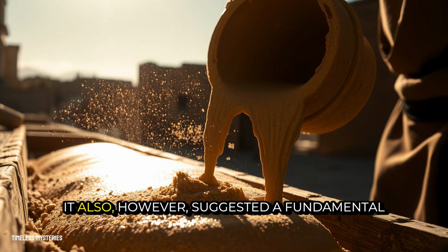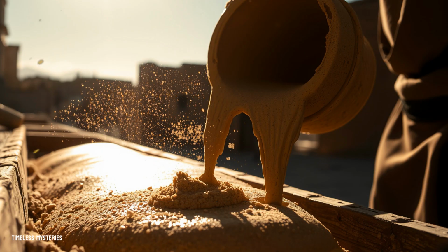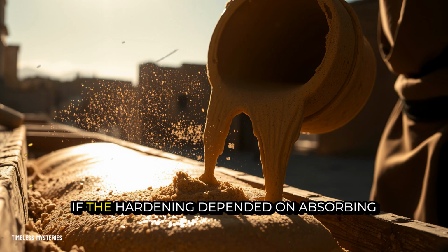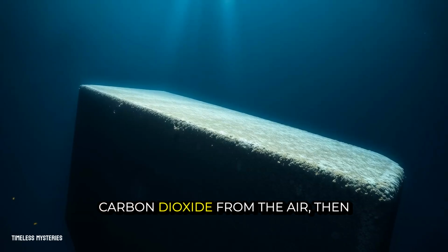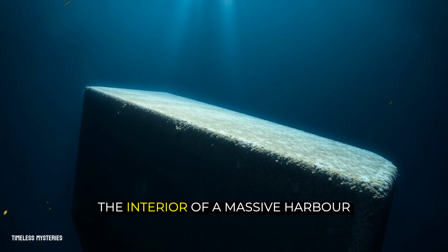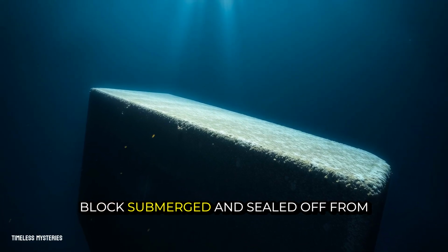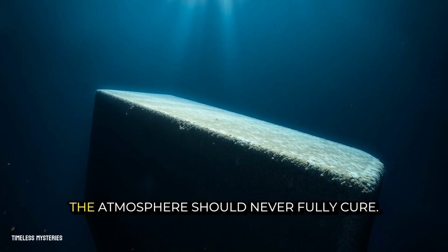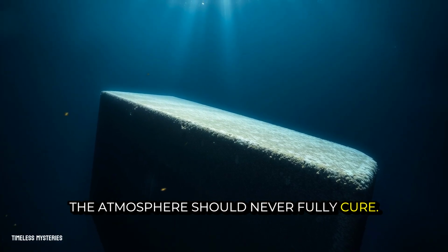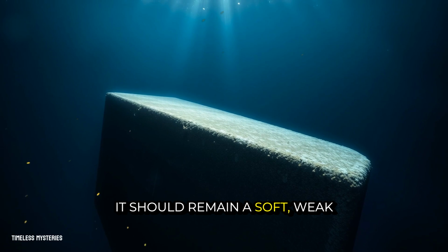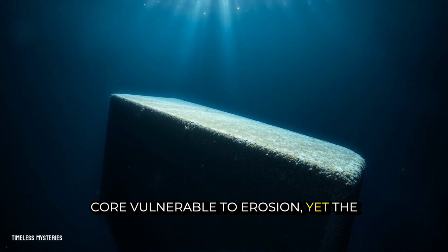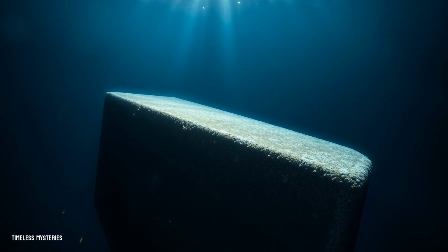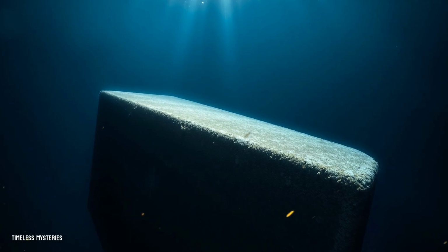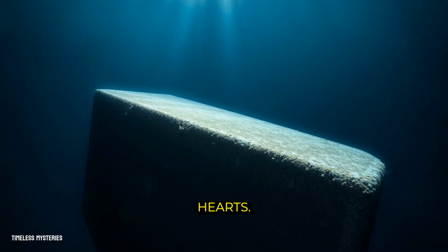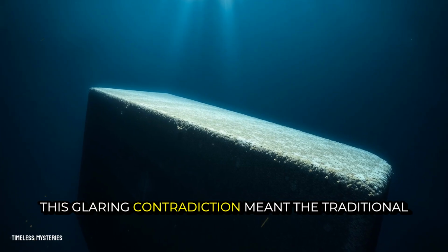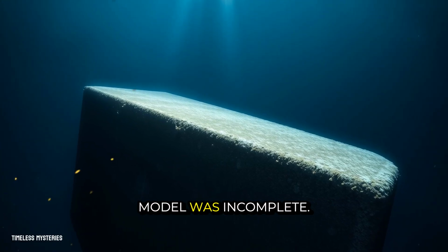It also, however, suggested a fundamental weakness. If the hardening depended on absorbing carbon dioxide from the air, then the interior of a massive harbor block, submerged and sealed off from the atmosphere, should never fully cure. It should remain a soft, weak core vulnerable to erosion, yet the opposite was true. The most durable, solid parts of the Roman piers are their submerged hearts. This glaring contradiction meant the traditional model was incomplete.